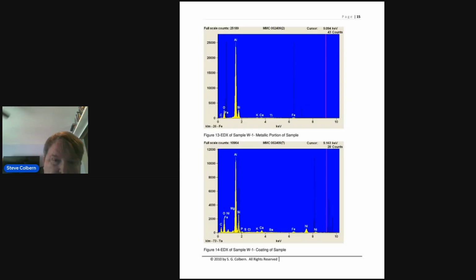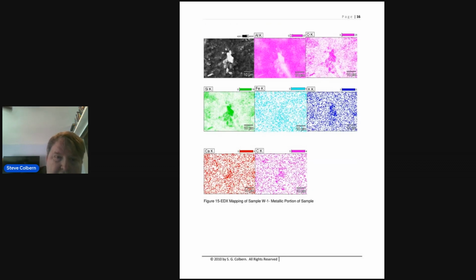Yeah, here's sample W1. The surface had more nickel and phosphorus, oxygen. So oxides and phosphates and chlorides, perhaps. There's some sulfur in the surface coating as well. So, next page. Here's some EDX mapping. The elements look like they're pretty well homogeneously dispersed, with the exception of the silicon. Some of those crystals or structures on the surface were apparently silicon dioxide.